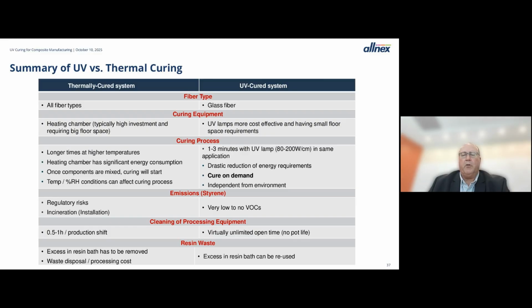From a styrene standpoint, UV cured systems can be made easily styrene free. Thermally cured systems, that may or may not be the case. Cleaning is a lot easier with UV because unless it's exposed to the UV energy, it's going to still be a liquid and very easy to clean up. And there's a lot less resin waste in UV systems because until it gets exposed to UV, the material can be used as long as you want. So some advantages there for UV curing.